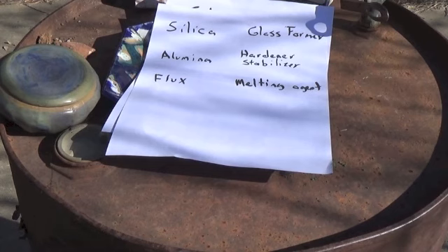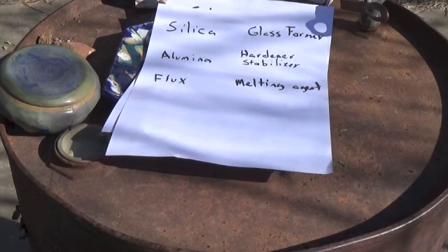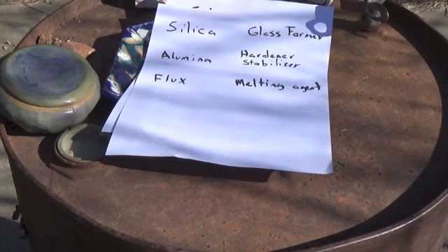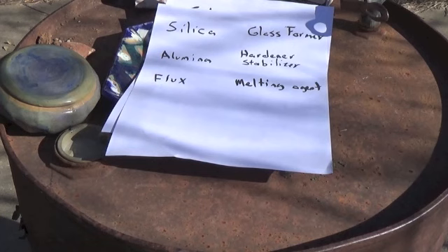There's a natural one called Gerstley borate, but to get a really high borate level, usually they have to turn it into a frit, which, as I said before, is a glass that they add the chemicals to, dry, melt it, and turn it into a glass, and then they grind the glass back down into a powder, and that way it's stable because then the borate is already fused to the silica and the alumina and the other things that are in the mix.